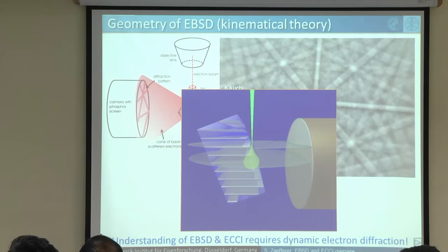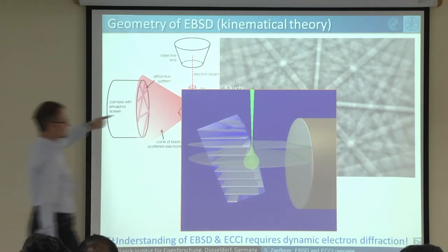But now if you pay attention to my speaking, then you would expect that here is the intensity of these Kikuchi lines, and everything else should be black. So we would expect two bright lines running over the phosphor screen, and the rest should be dark. We see the opposite. We see two black lines running over the phosphor screen, and the rest is bright.